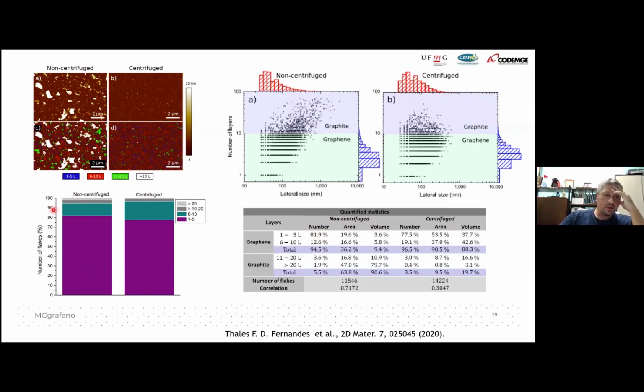Okay, so this is translated in this chart here. We have the percentage of each type of graphene: the purple is 1 to 5 layers, the green is 6 to 10, and the gray is graphite, okay? We see that in terms of numbers, we have a lot of graphene particles for both samples, and they look very much alike, but they're not the same. We can see from the AFM images that they are not the same.